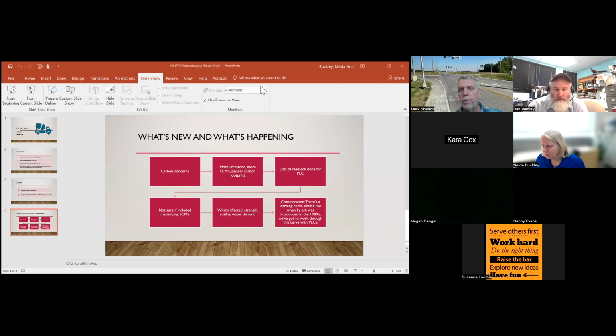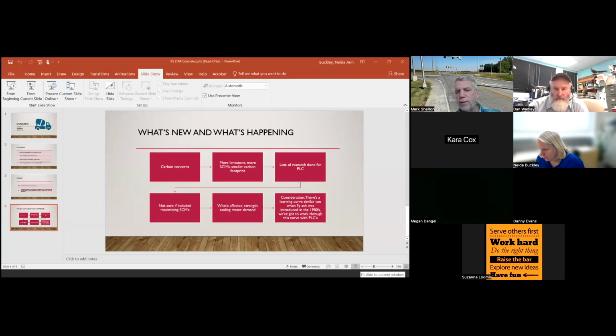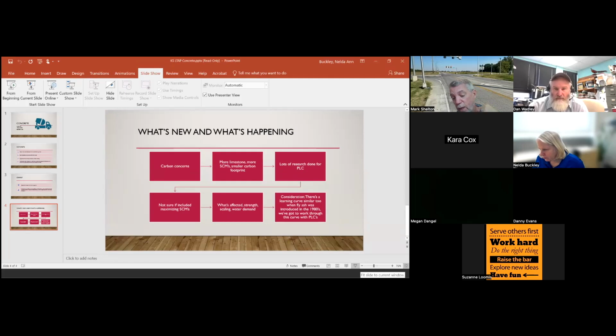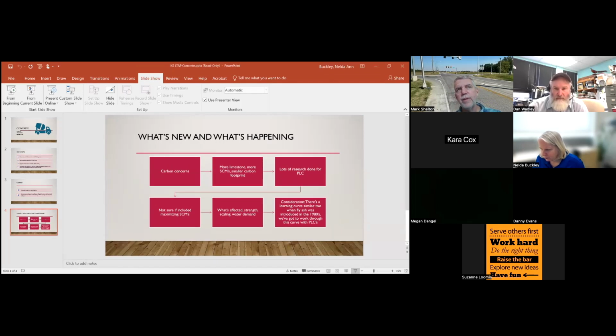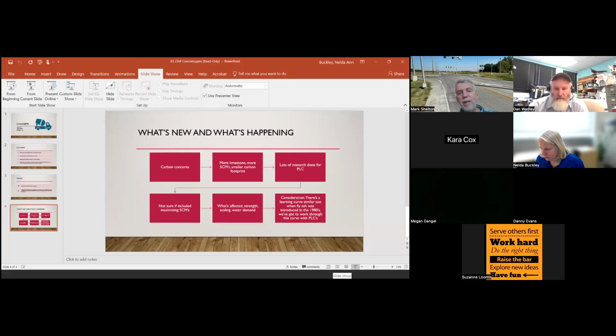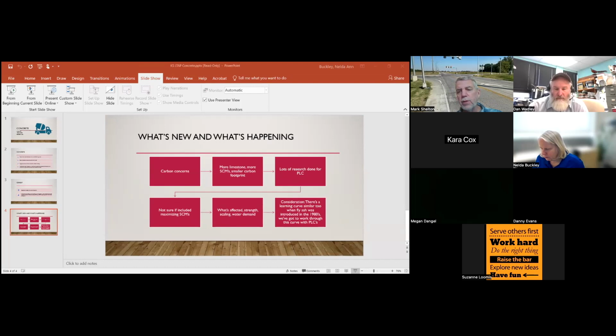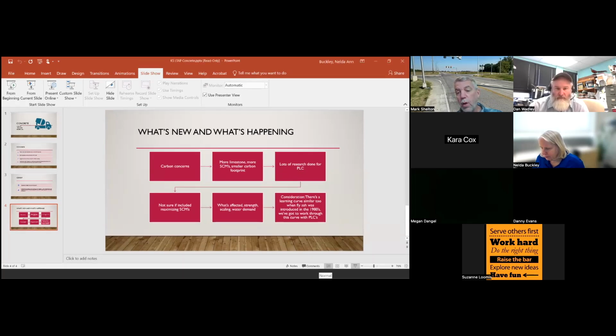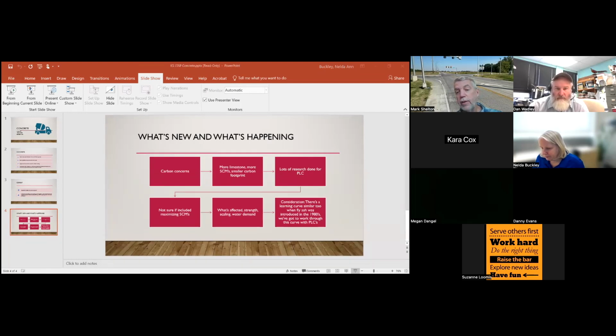I think what we heard from the very beginning is, just look at our Portland limestone cement just like it's a Type 1. We're finding that in practice, when you include the changes in the dosage of admixtures and the amount of the supplemental cementitious materials that are used, we're not seeing exactly the same results. And that goes to that last box, there is a learning curve. One of the better comments that I heard, and it stuck with me, is that back in the 80s, when fly ash was added to concrete mixtures, there was a learning curve that the industry went through to figure out exactly how to use this material to get the characteristics of the concrete we wanted.